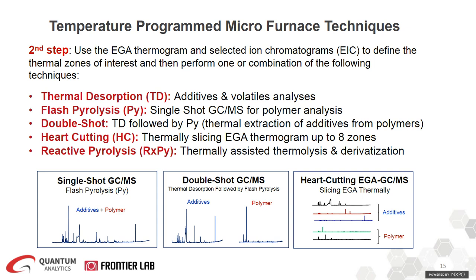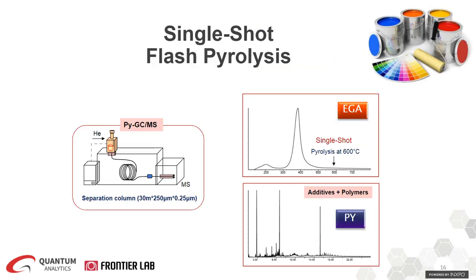For example, in the cases that we showed, I could show that here on a slide. In this case, on a single shot, you see how the more intense peak is coming off around 550 or 600 C. So that will be the place you want to have your flash pyrolysis done. If you would have chosen 400, you would not really create the fragmentation of the polymer. So you want to break down the polymer into fragments at a proper temperature from your EGA.